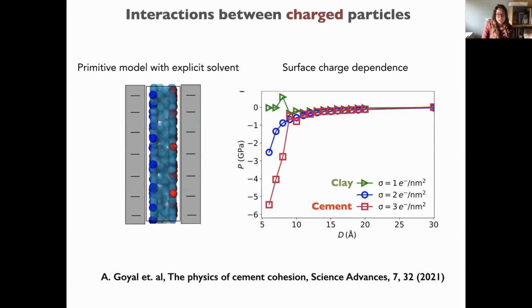So here, for example, by changing the surface charge, we can also devise interactions for clays that are correctly repulsive. And by increasing the surface charge, we see that in the case of cement, we have a very strong attractive interaction that goes down at a pressure of gigapascals, which is actually what is known from experiments for cement.